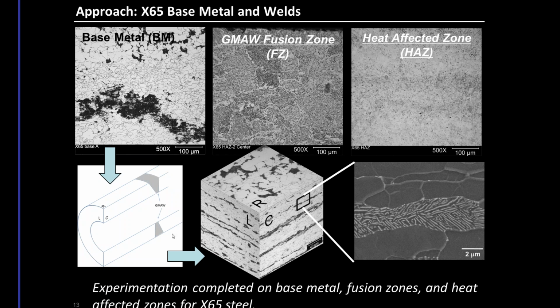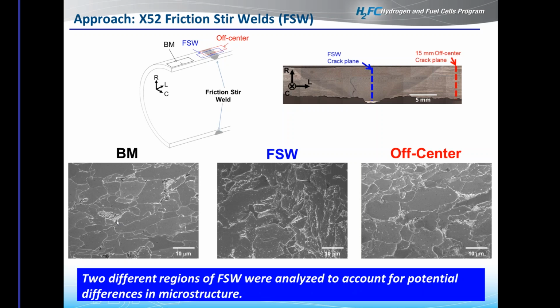And I've used this schematic, and I'll use it throughout the talk, to help guide where specimens were extracted with respect to the weld, and it shows the different orientations. So that's what these L, R, and C values mean. So we also looked at a friction stir weld, and this was a thinner pipe, a thinner walled pipe, I should say. We extracted specimens out of the center of the fusion zone, as well as an off-center region, and then of the base metal. And these dashed lines in this case represent the crack plane, and in this case they'd be moving in and out of the screen. So that's where we situated the specimens so that we'd be testing a more or less uniform microstructure as the crack progressed through the material.